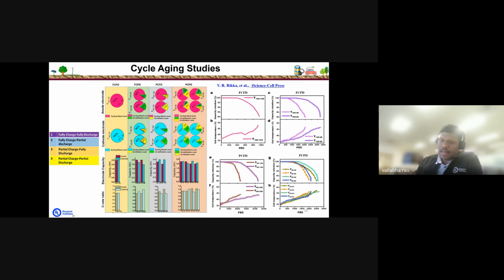So during the electrochemical cycles, even at the interfaces of the anode or cathode, if the lithium ions are consumed, then the extra stored lithium ions can participate in the electrochemistry, which can actually enhance the cycle life. If you look at the right-hand picture, these are the cycle life studies over the cycles. For example, we can see the capacity retention from the first cycle over the cycles for each test condition.